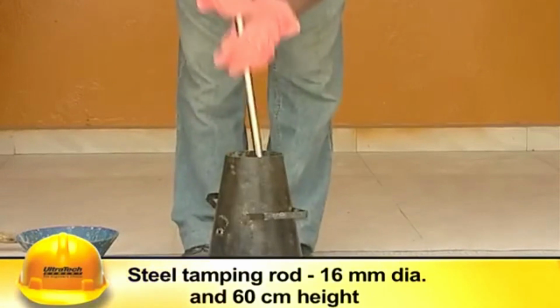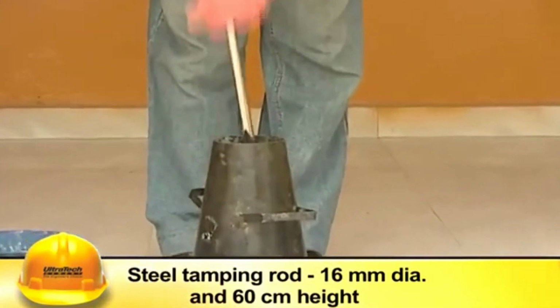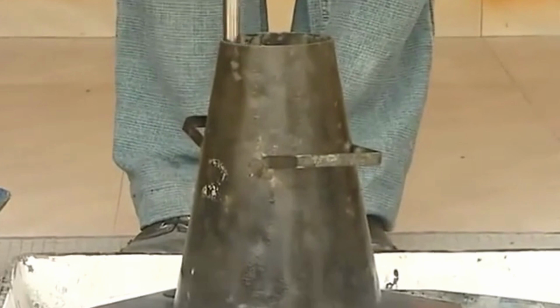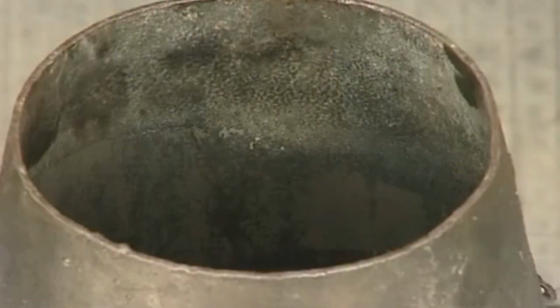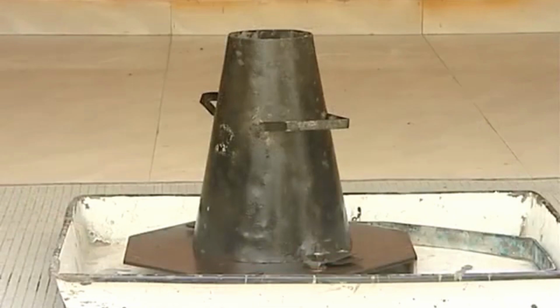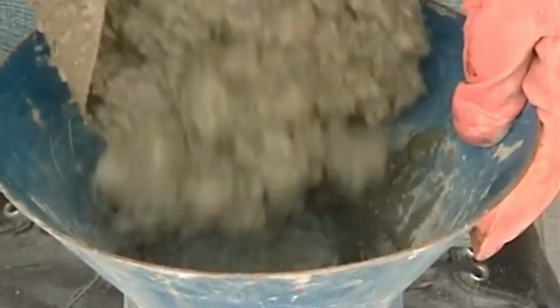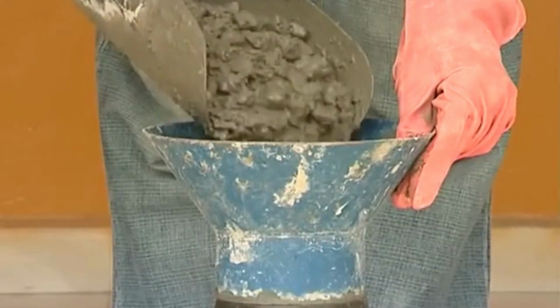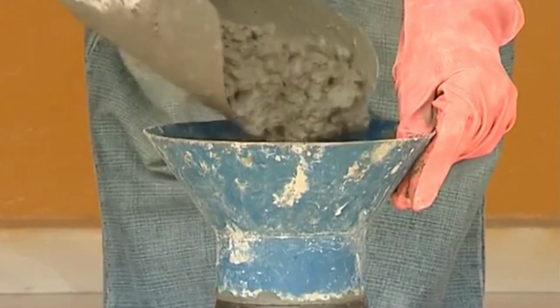Now we will see the procedure. During the slump test, the following steps are followed. First of all, the internal surface of the mold is cleaned and kept free from moisture and from old sets of concrete. Then place the mold on a smooth, horizontal, rigid, and non-absorbent surface. The mold is then filled with fresh concrete in 4 layers, tamping each layer 25 times with a tamping rod, and level the top surface with a trowel.